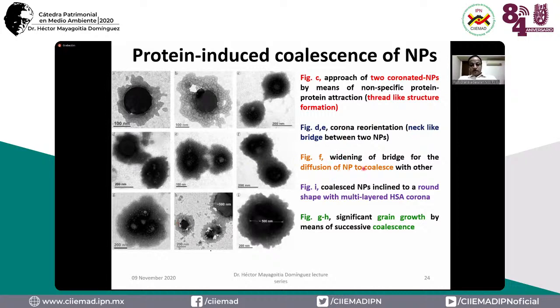Then F is the widening of the neck bridge, diffusion of nanoparticles to coalesce with each other, and G and I show the coalesced nanoparticles inclined to a round shape with a multi-layered human serum albumin corona. G and H show significant grain growth. There is a significant growth of this corona layer on the nanoparticles, so that the material will be sensed by the living cell as a self material. It won't recognize it as a foreign body. If it recognizes it as a foreign body, then there is a problem with the immune system. So it will recognize it as a self material.